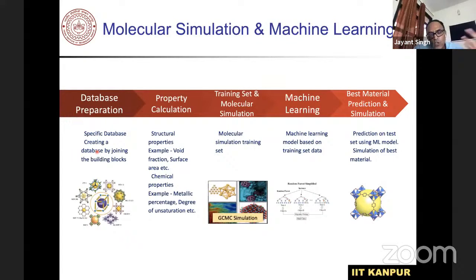And then the second thing is, for each of the materials which we have fictitiously considered, as well as those which were in the database, we calculated the properties. These properties are nothing but the void fraction, surface area, chemical properties, metallic percentage, and so forth. For a subset of the database, we trained with molecular simulation. For each of them, we have done a grand canonical Monte Carlo simulation, which is nothing but a simple adsorption-desorption kind of simulation method. Subsequently, we train a machine learning method, and then we try to predict the best material out of it. So this is a typical mechanism which we adopted.